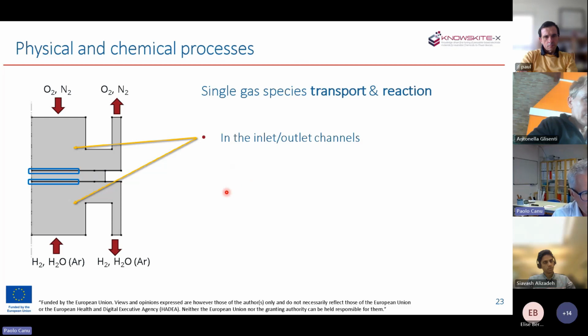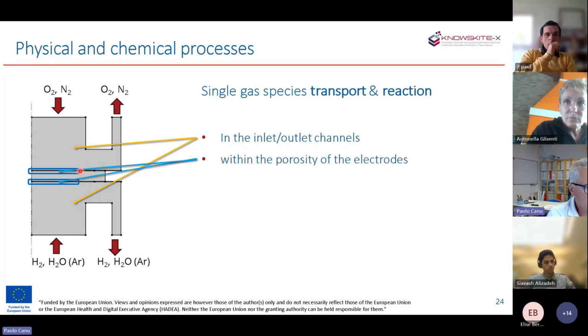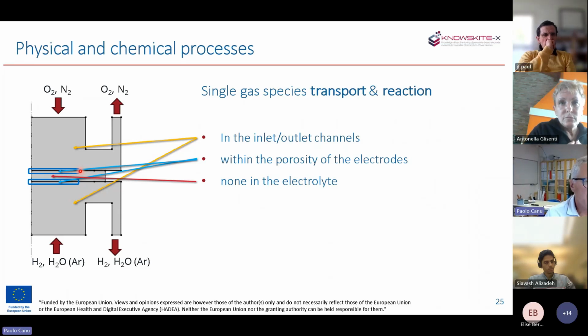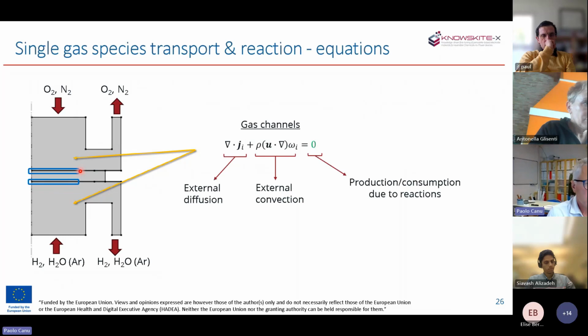It is more important to look beyond the total gas flow to the single gas species that may travel and react. Single gas species are in the gas compartment. They are within the porosity of the electrodes, and there should not be any gas within the electrolyte if it's operating as expected. So the description of how single species move in the gas compartment is given at steady state by this equation that basically says that the single species might diffuse or might move together with a whole stream, and they cannot be consumed or produced within these domains. There's no reaction. The reaction is within the electrodes.